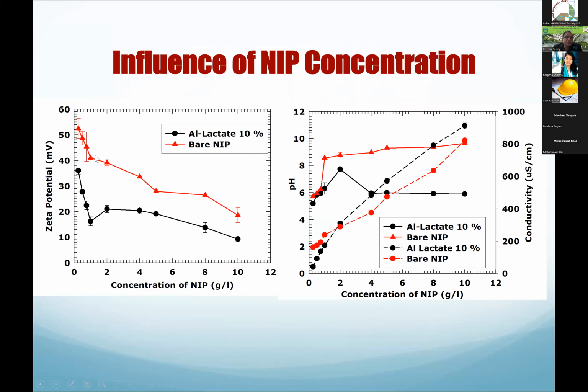Again, you see that the zeta potential decreases. Bare NIP, you see that one, it decreases. And if you have aluminum lactate 10%, it decreases, slightly increases, and then it decreases. Again, you will see a lot of shift in the pH values depending upon the concentration, depending upon the type of lactate that you're using. Aluminum lactate 10% or bare NIP. And here what I'm showing is the pH is one and conductivity is the other numbers that I'm showing.